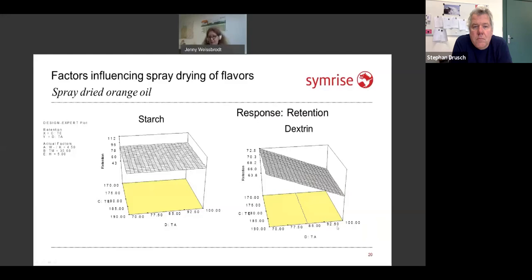For the dextrin, we can see that the outlet air temperature should not be too high. Here again, we have this effect of internal mixing. It should be moderate, so that you don't lose too much of your orange oil. The inlet air temperature, whether it's 190 degrees C or 170 degrees C, doesn't make a difference at all.